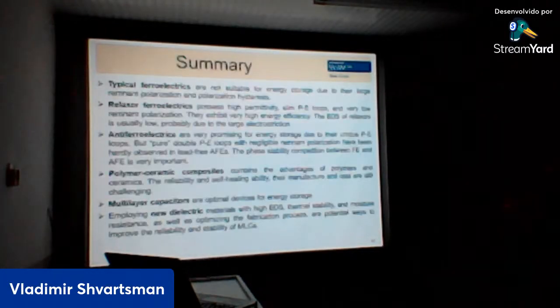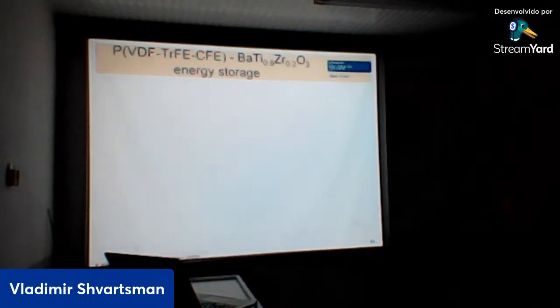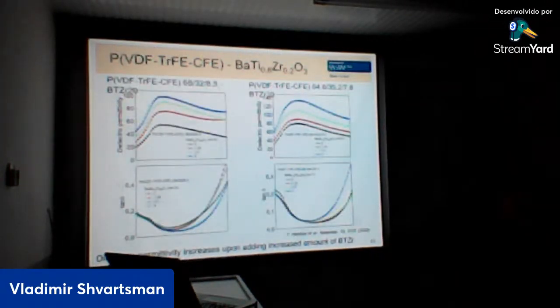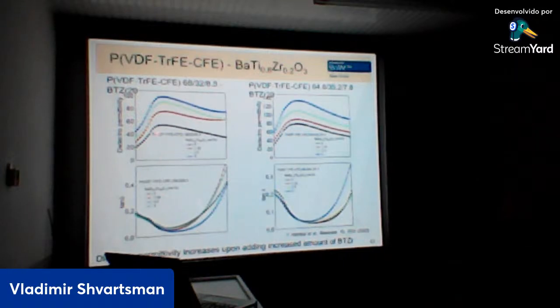Just to give an idea, you see, we started from the beginning with about 50 relative permittivity, and we can improve it twice. But if you start from 5 or 10, you will still obtain not a very high value. But I think there is also research with non-ferroelectric polymers, just linear dielectric. How does the dielectric breakdown compare between polar polymers and non-polar polymers?